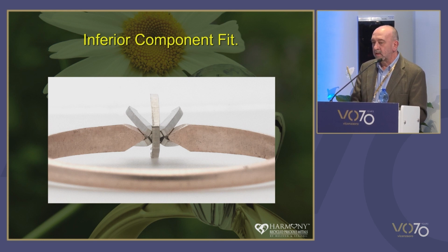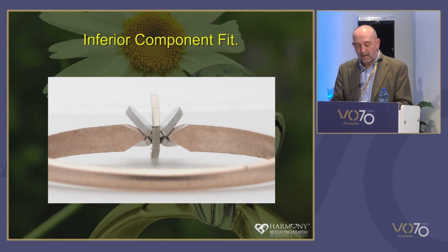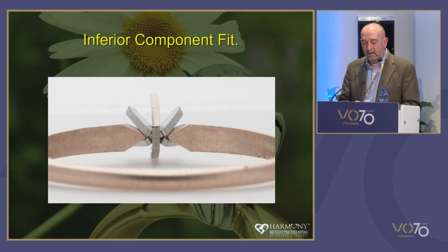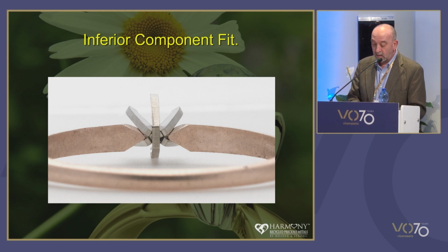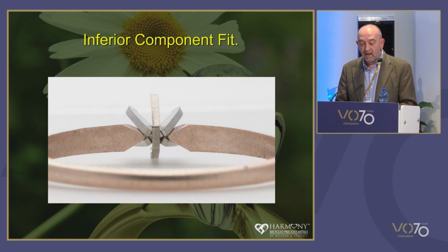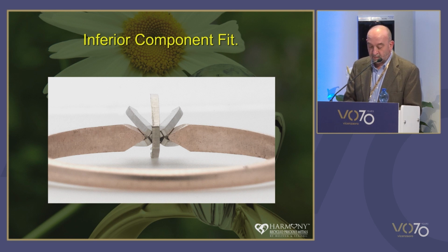So we analysed the production process and we found out that the assembly department had started to pre-finish all the components before they assembled them. It saved them time during their production process, but unfortunately, the effect was to round off all the sharp edges, making the overall fit of the components inferior, as you can see from this last picture here, large gaps.